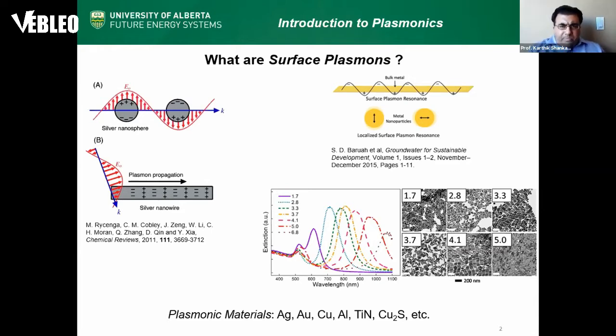Now, plasmonics is the quintessential nanoscale phenomenon. The surface plasmons are generated by nanostructuring metals. So either you have thin films or gratings for SPPs, or noble metal nanoparticles for LSPR, and it's gold and silver that have surface plasmon resonances at visible wavelengths. And there are a few other materials which I point out here.